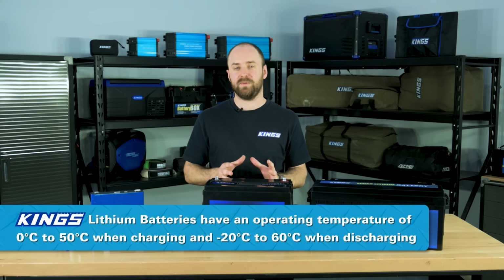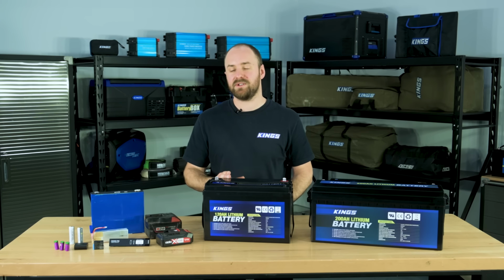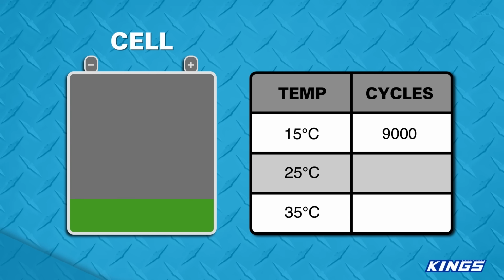For lithium iron phosphate charging, ideally you'd keep your battery temp below about 40 degrees. In one study, the same cell, when fully discharged and charged over and over at 15, 25 and 35 degrees, was able to perform about 9,000, 7,000 and 4,500 cycles respectively. So keeping your battery temperature down can make a big difference.